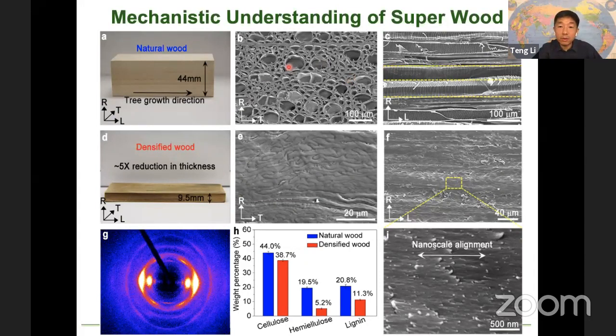And not only those, now if you look sideways, from the side, you will see that along the cell wall of the wood, there are a lot of small pits that serve as defects as well. In the next page, I'll show you a better image. Now, after the densification, as you can see in E corresponding to B, imagine that B is collapsed, pressed from the top to bottom.